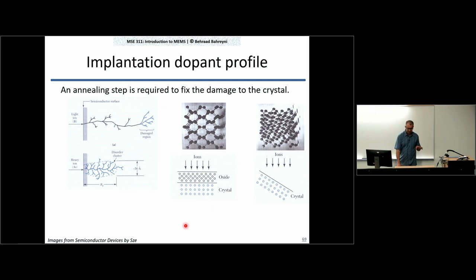The other way of doing it is to have a thin layer of, let's say, silicon dioxide on your surface. So you put, let's say, 50 nanometers of silicon dioxide. Your atom comes down with a lot of energy. They go through the silicon dioxide layer first, but silicon dioxide is amorphous, so they get a little bit of randomness in their direction. They don't go that deep into your silicon anymore. Instead of going straight down, they now come with somewhat of an angle when they go through that silicon dioxide layer, and that gives you more control over the depth. Now, the issue of damage to the crystal is still there.